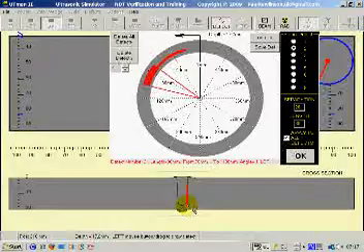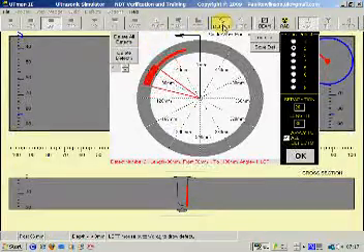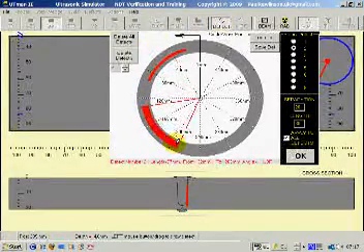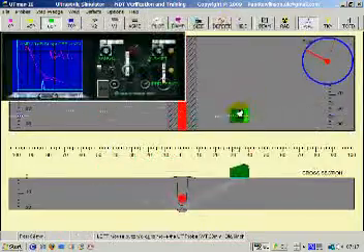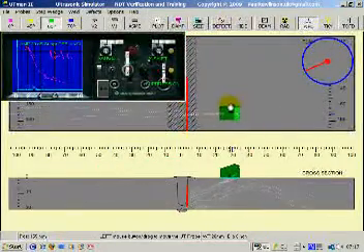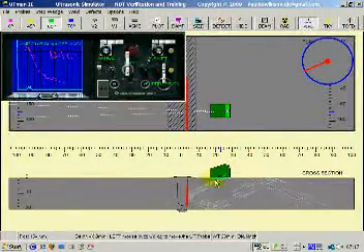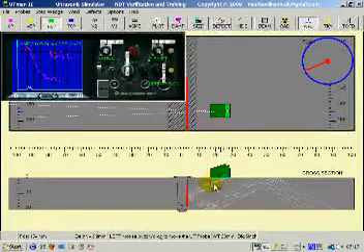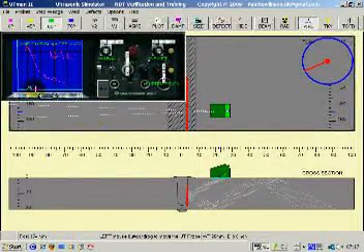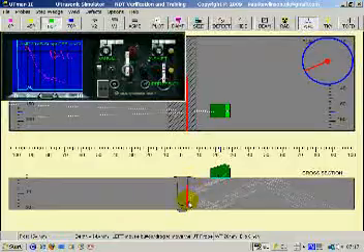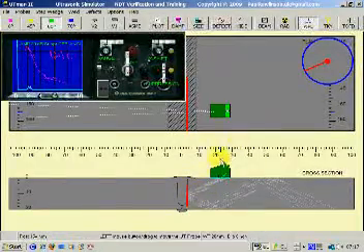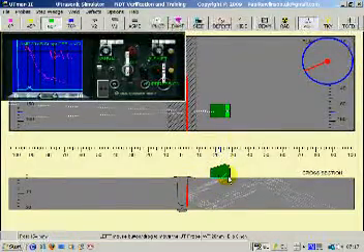Using the right mouse key, and I'll draw it about here on the circumference. See, the response is very smooth, but it's a very, very low amplitude response because the orientation to the beam angle is not exactly 90 degrees.